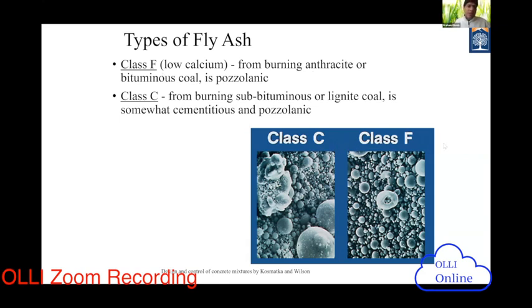You see both types of fly ashes are spherical in nature. Cement particles are also spherical in nature, but the advantage here is that fly ash particles are smaller than cement particles. So when used with cement particles, they fill up the voids. When you fill up more voids, chloride has a hard time diffusing through the concrete, as you can imagine. More voids, an easy path of ingress. Fewer voids, it becomes more impermeable. When it becomes more impermeable, there is less diffusion, and less diffusion means we get higher initiation times.